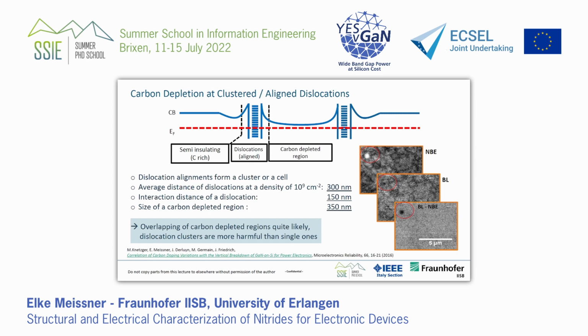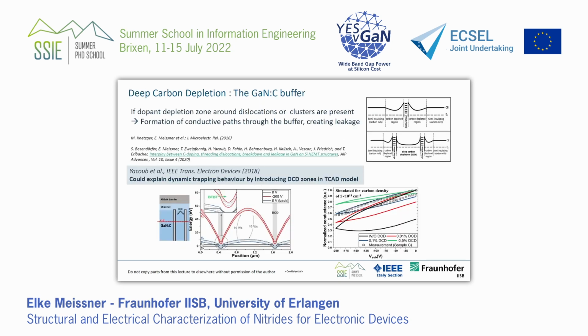You say, okay, the interaction distance of a dislocation is so-and-so, where the strain fields overlap and grab even more carbon, and the size of such a carbon depleted zone has some size, and we can measure it. And now we say, okay, it can also happen that carbon depleted regions are overlapping. Then you have this very deeply depleted region. They are even more N-type conductive, and it's more harmful than if you have single dislocations which are isolated somewhere.